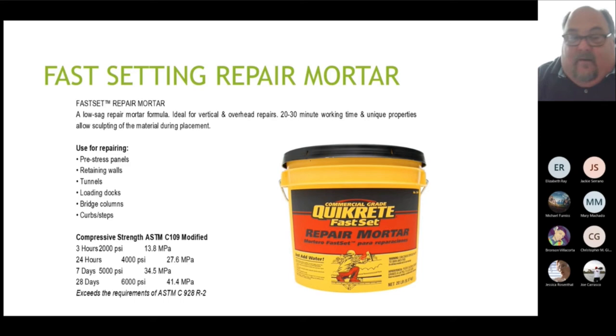As far as water, usually it's about 3 quarts of water. This one is called a plastic consistency, so you want to mix it about like peanut butter. And I mean the good old peanut butter, not the new stuff, which isn't good for you. You want a peanut butter, almost oatmeal consistency, and you get that with 3 quarts of water. You're going to want to damp cure this for the first 24 hours.